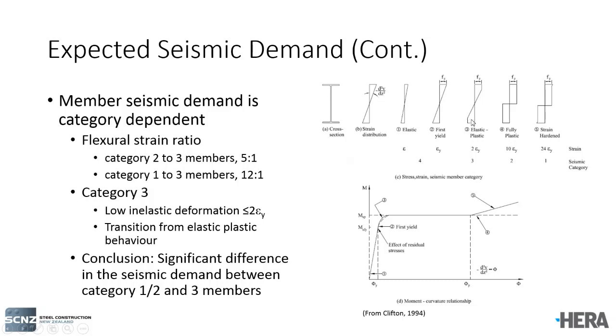Category 2 members, we have a fully plastic section, and the strain demand in the section would be in the order of about 10 times the yield strain. Once we get to category 1 members, we are now seeing strain hardening, and we're getting strain demand in the order of about 24 times the yield.